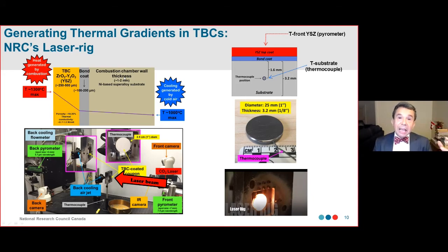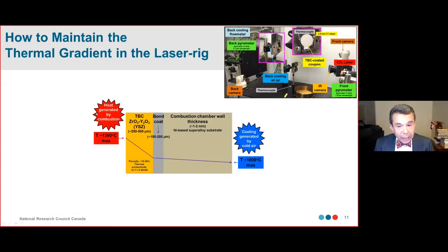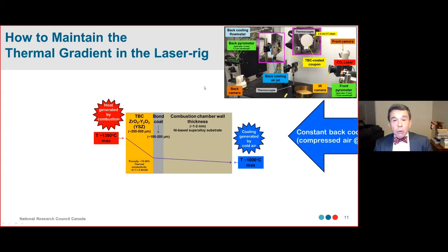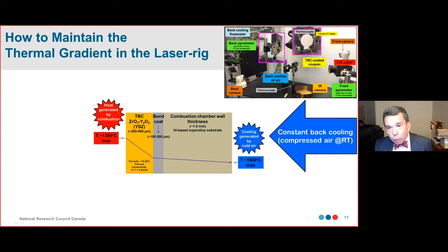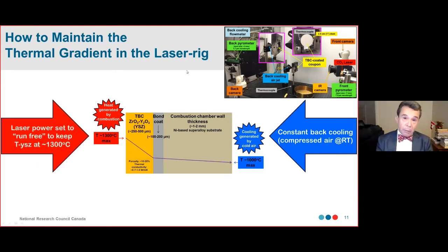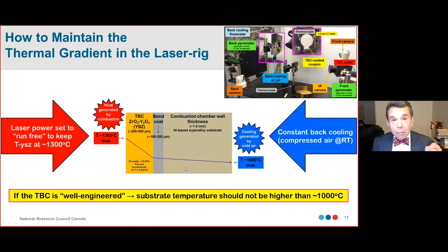But how can we maintain the thermal gradient in the laser rig? You have to generate the heat and you have to generate the cooling. So we have a constant back cooling at room temperature. We have this nozzle here, with compressed air at room temperature cooling all the time. And the laser is a computer-controlled system. We tell the laser rig, please keep the temperature of the YSZ TBC at 1,300 degrees Celsius. Based on the pyrometer measurements, the laser rig adjusts its power to keep this temperature at 1,300 degrees Celsius. This way, we generate a thermal gradient. If we make a good TBC and put it in the laser rig, if the TBC is well engineered, the substrate temperature should not be higher than 1,000 degrees Celsius. That is the maximum temperature that the substrate can handle.